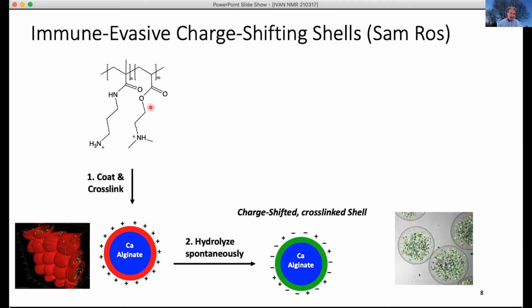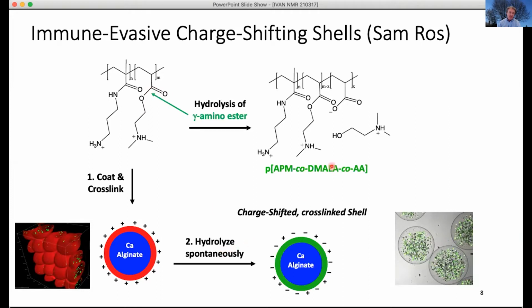But we've designed a spontaneous hydrolysis feature into these groups. This ester here hydrolyzes over a couple of days, and that allows removal of a number of these cationic groups. We generate anions. The overall polymer shell now becomes overall neutral in charge, so these are now immune evasive shells. But the problem is, of course, we need to be able to track this.